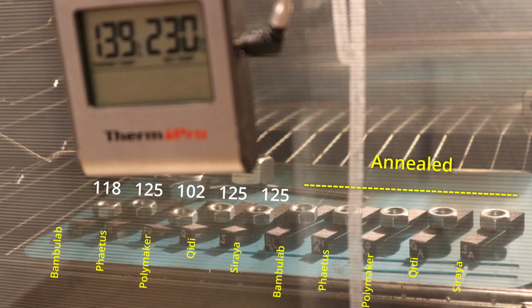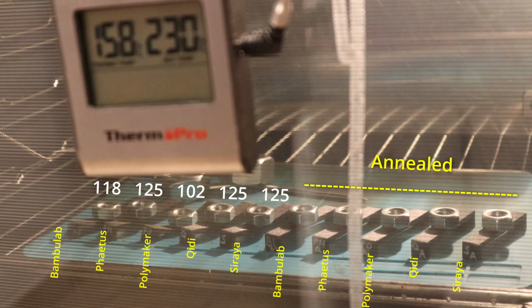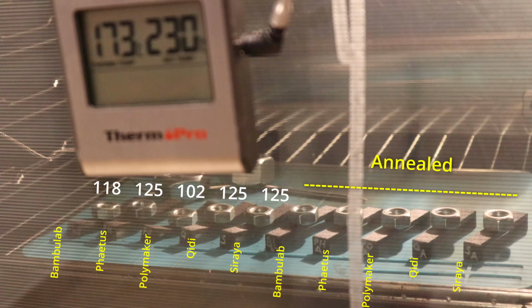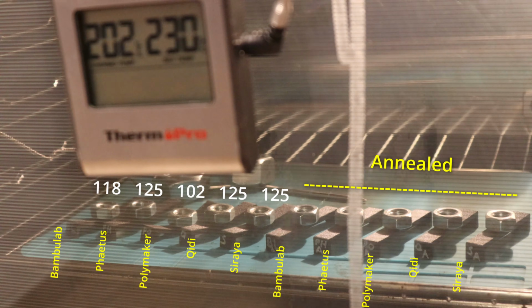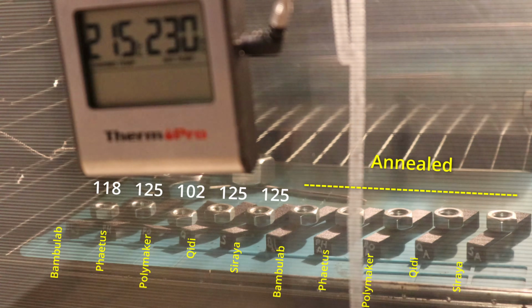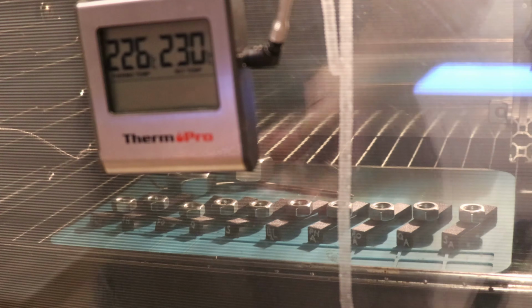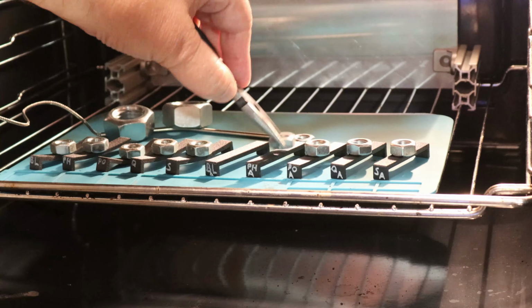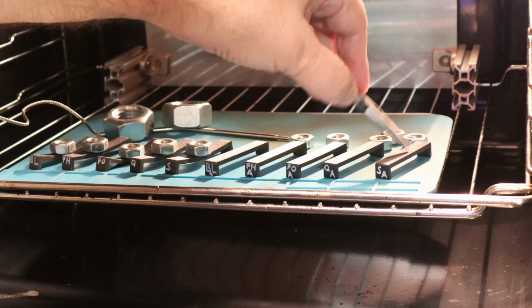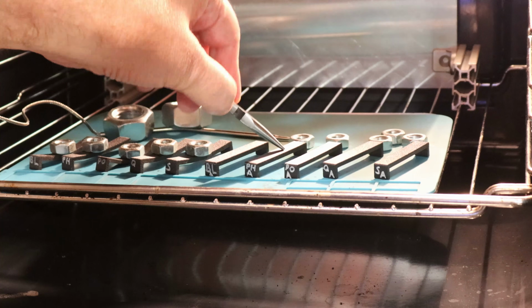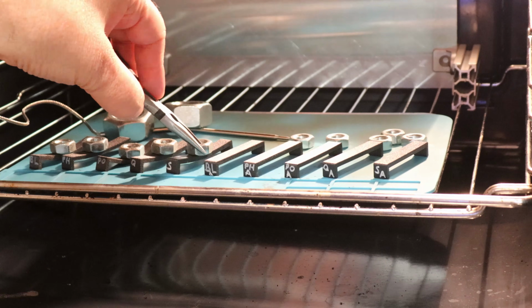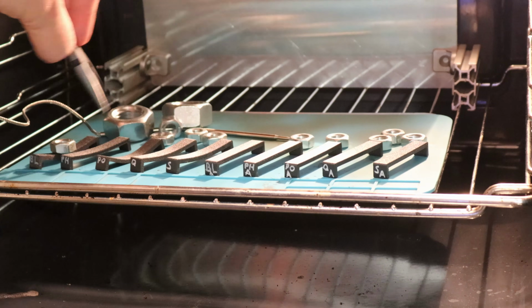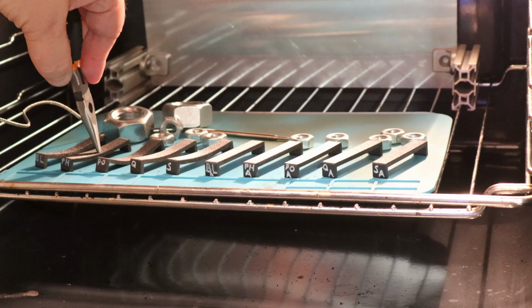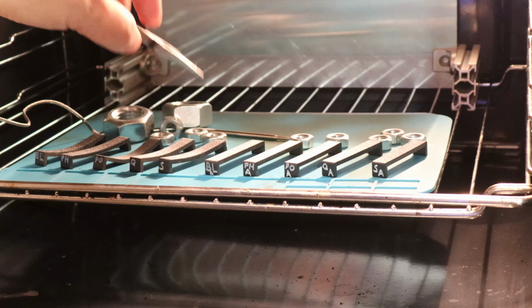However, the deformation stopped shortly after it began. You will see later in the video, I think this happened because they became annealed. Once crystallization occurred, the deformation stopped completely. I stopped the experiment at 226 degrees Celsius, and the annealed versions, by feel, are completely hard and without deformation. I also checked the regular materials, and by feel they are equally hard. Probably they became annealed at the beginning of this test.